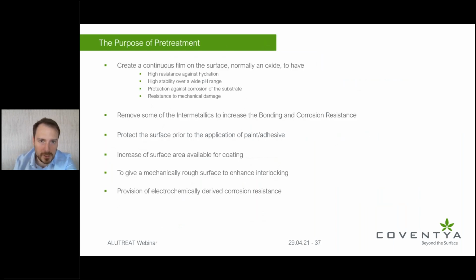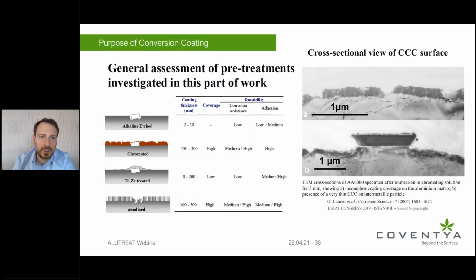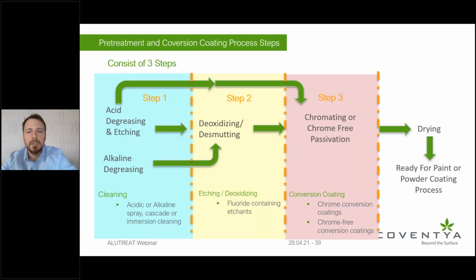failure. In order to correct this situation and give the paint a much more suitable ground in terms of roughness, cleanliness, and chemical compatibility, we are using pre-treatment, where we use degreasing and also a conversion coating, which could be based on classical chromating, which obviously gives very good results, but we also have titanium, zirconium, and even special anodizing applications that are applied underneath the paint in order to improve the adhesion and also the corrosion performance, especially in marine applications.